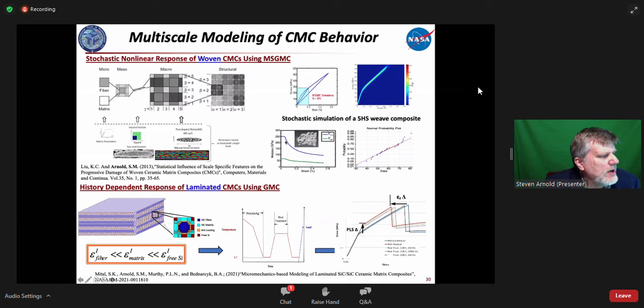And we're also showing here the in-plane modulus and the out-of-plane modulus, and you can see we're able to pick up the distinct difference between those two due to void pattern within the CMC, but also you can see that the evolution and degradation of those modulus do take place, and they're different as strain is increased. And of course, then we can look at the probabilistic aspects of the stress strain curves and the properties as well.